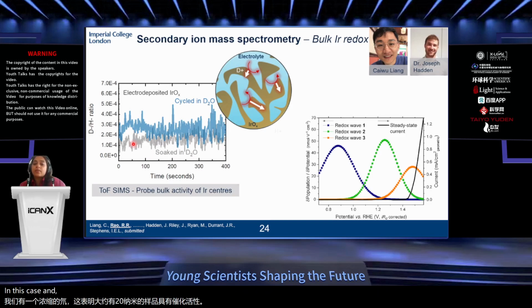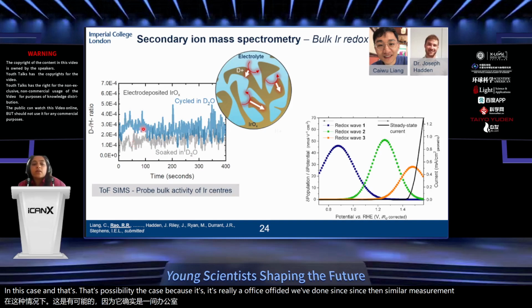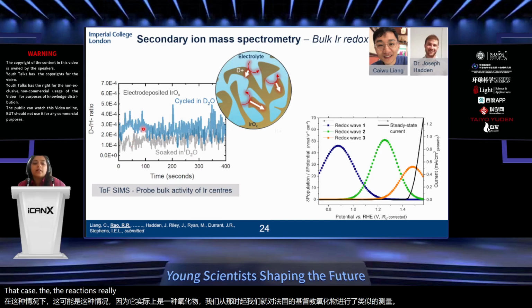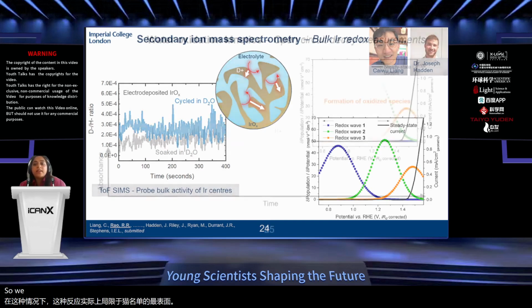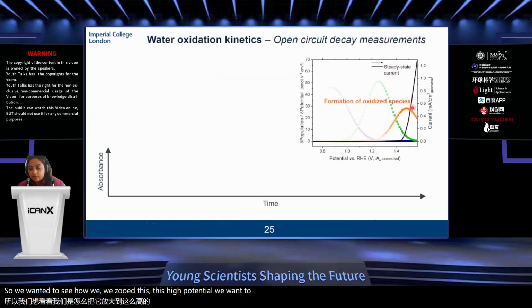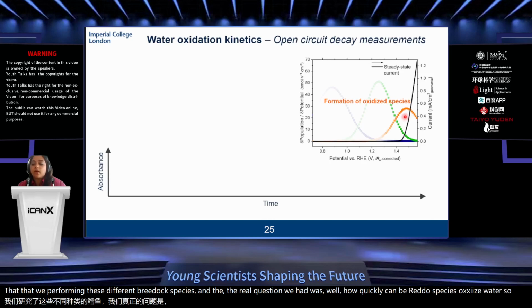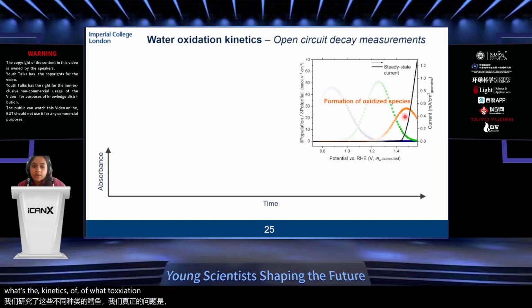And that's possibly the case because it's a really amorphous oxide. We've done since then similar measurements on a crystalline oxide and found that in that case the reaction is really confined to the very surface of the catalyst. So we wanted to zoom into this high potential, where we are forming these different redox species, and the real question we had was, how quickly can these redox species oxidize water? So what's the kinetics of water oxidation on these redox species?